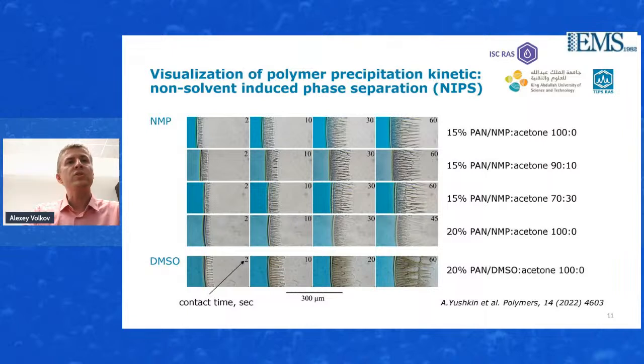The dye was added into the water to see how the water goes inside of the membranes. And if we have a look at the first three rows, we can see that increasing acetone from 0 to 30% in NMP leads to a quite noticeable change of the morphology of the membrane. And the same thing in the last two rows: replacement of NMP by DMSO also changed the porous structure of the membrane a lot.